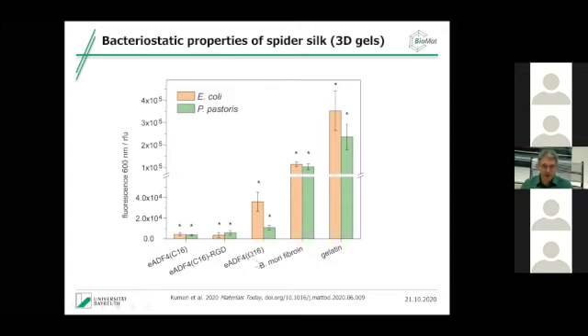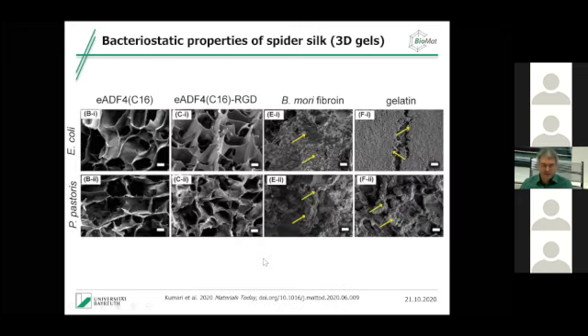And even if we modify this silk here, if we remove the charges completely, eADF4(C16) is uncharged silk, then you see that we lose some of the ability of repellency. But be aware, here's a break in the y-axis. So this is orders of magnitude higher in silkworm silk and in gelatin. And this is how it looks like.